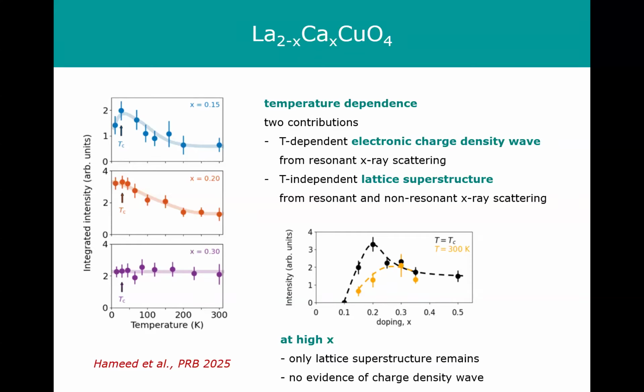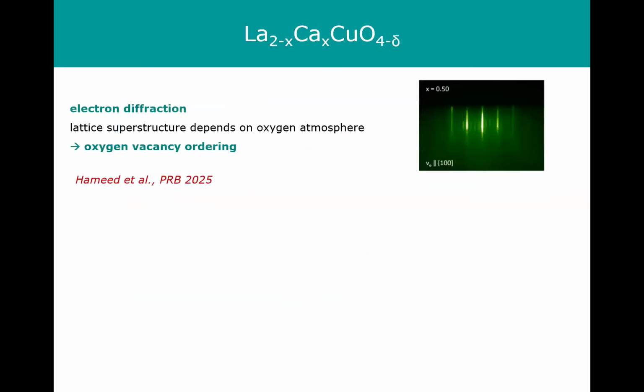We have this lattice superstructure at high temperatures, and that sort of seems to template a charge density wave structure that you then only see in resonant X-ray scattering. You need the resonance to actually visualize this charge order. Okay, and now the question is what is the origin of this lattice superstructure?